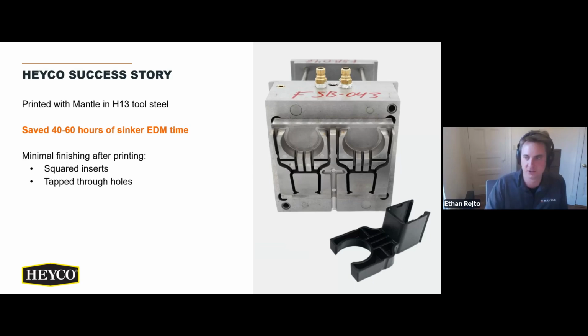They printed these inserts with Mantle. You can see the actual part there on the right, all of those ribs that were able to be molded off the printed tool. And they estimated they saved 40 to 60 hours of sinker EDM time by doing this and required very minimal finishing after printing. They just squared the inserts and then tapped the